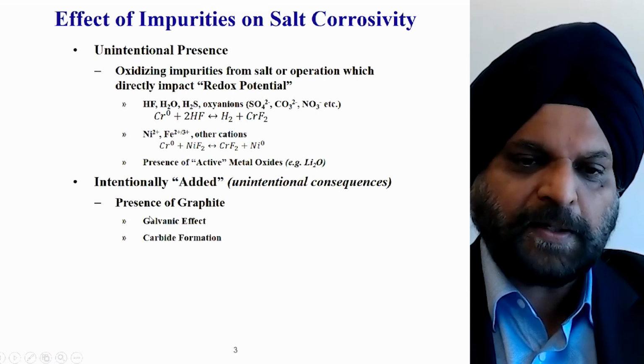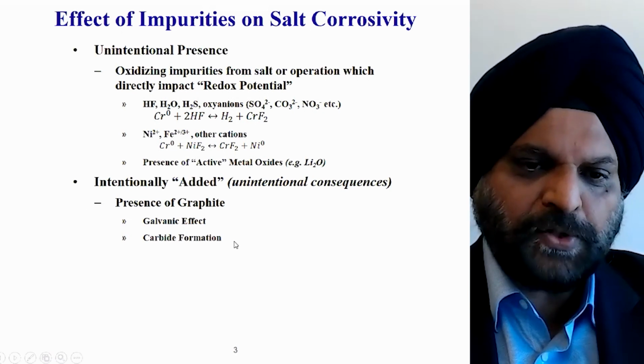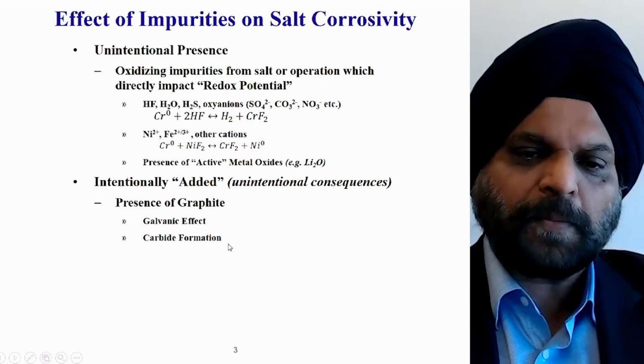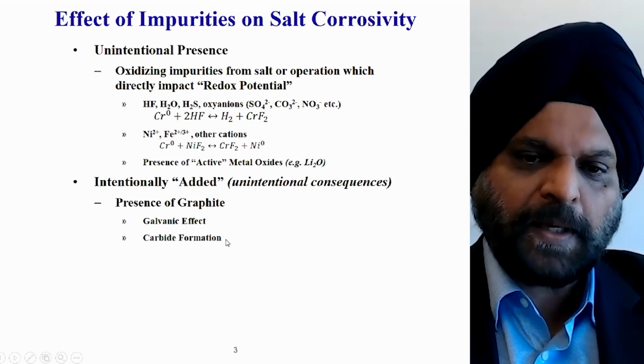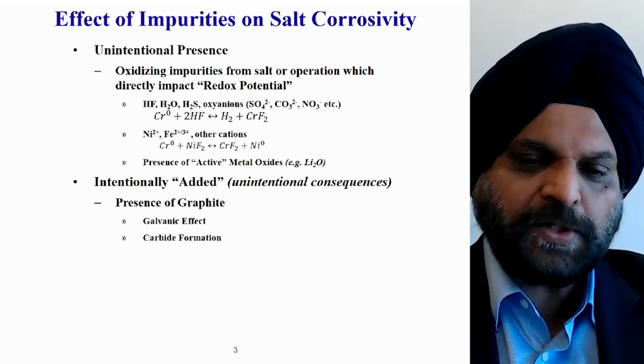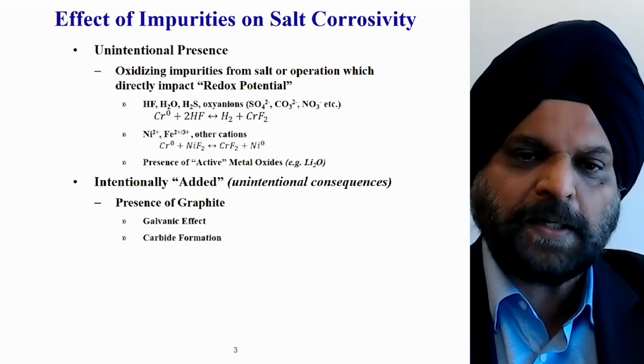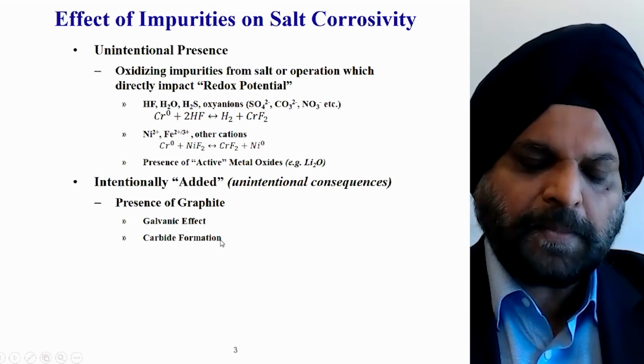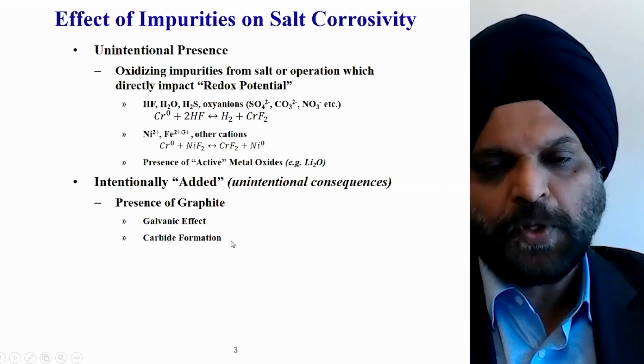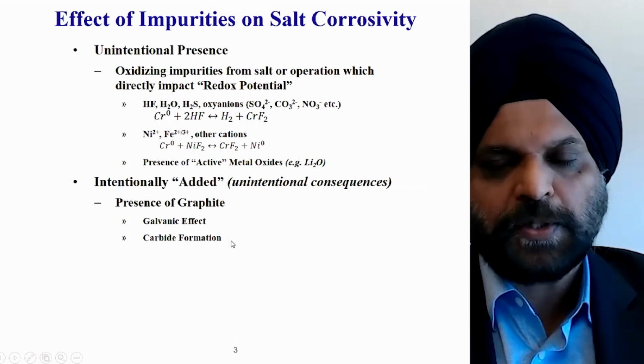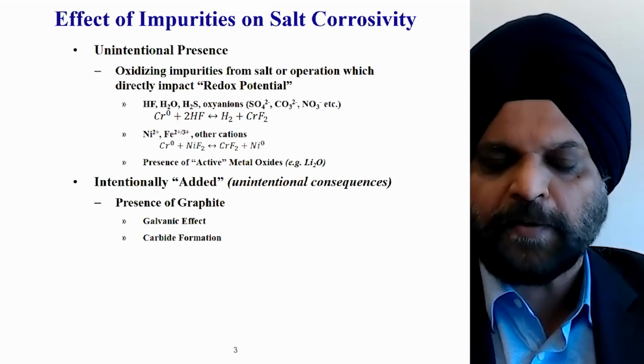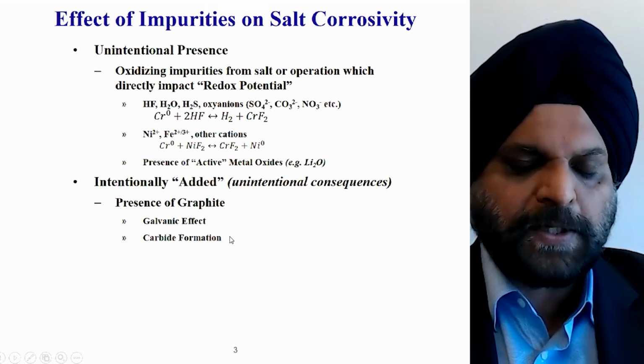corrosion can be different. Kevin's recent work has shown that you can actually form carbides because we are carrying out reactions at 600 to 700 degrees Celsius in MSR reactors. At that temperature, if graphite is present on the alloy surface, you can actually have carbide formation at the alloy surface or wherever metal ions and carbon are available.